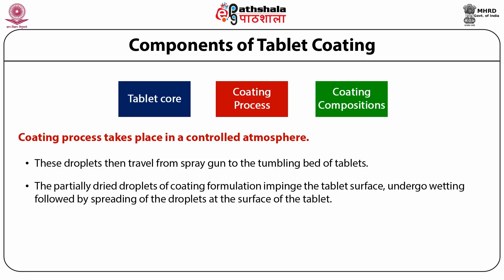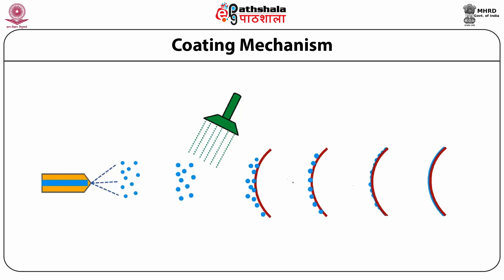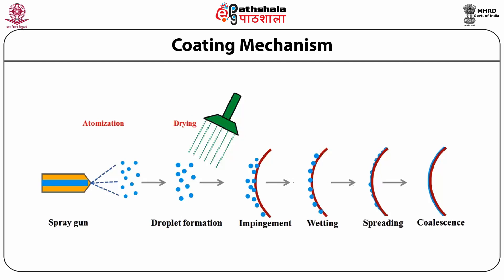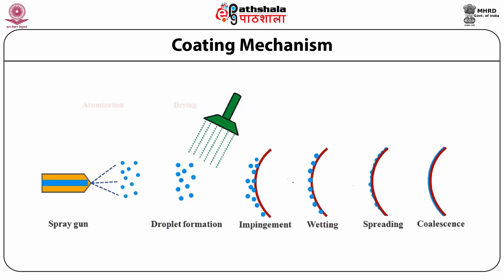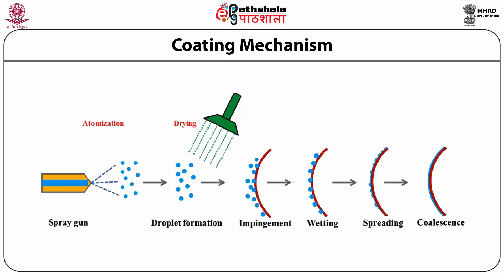Under the prevailing conditions, water will be lost and the droplets will coalesce over the surface of the tablet to form the film. The airflow is regulated for temperature and volume to provide controlled drying rates, while maintaining the coating pan pressure slightly negative relative to the room, providing a completely isolated process atmosphere for the operator. The successful application of the coating formulation provides the visual characteristic for the product, so the quality of the product may be judged on this final production step.